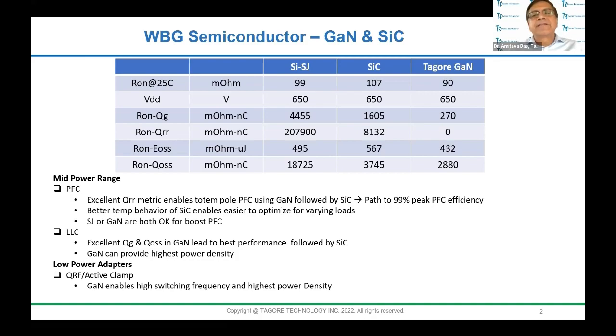In the PFC block, one very interesting trend is to use totem pole PFC. Essentially, you get rid of the rectifier bridge, and you can use this totem pole PFC. Unfortunately, because of the large QRR, you cannot use a superjunction MOSFET for totem pole PFC. Your only choice is either silicon carbide or GaN. So this is a very important area where wide bandgap material will excel, and this is the path to really hitting 99% peak PFC efficiency.